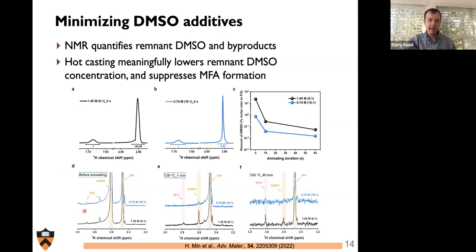Before annealing, we can see not only is DMSO left, but also DMF is there in smaller quantities. And then after 1 minute, we can see that the DMF is entirely gone, but DMSO, as we know already, is not. And the device that had the higher loading of DMSO in it, even after 1 minute, starts to reveal the presence of this MFA, this N-methylformamidinium cation, which we know to be problematic.